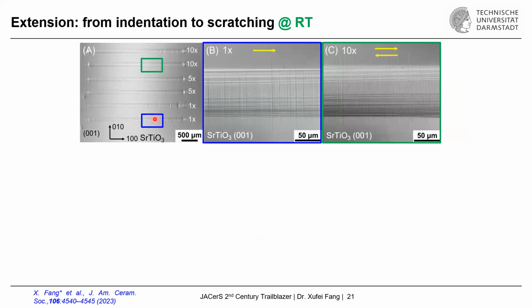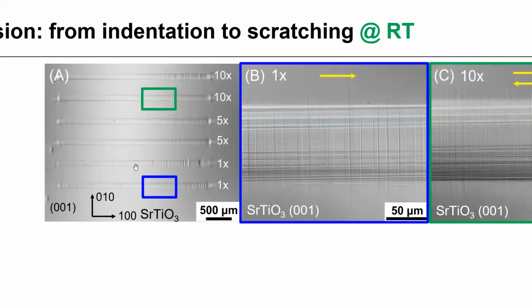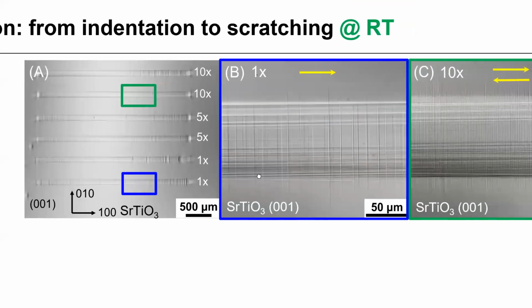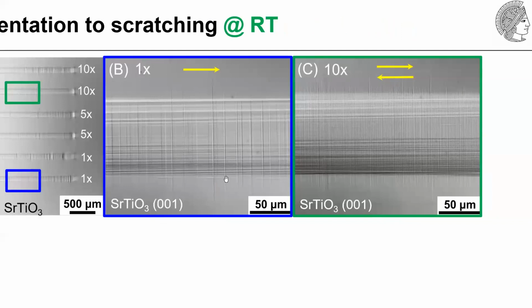Again, point loading using the indentation technique is not sufficient to generate a much larger plastic zone. That is why we started extending the indentation to scratching. And here I show you the cyclic scratching method. This is one cycle, just for reproducibility, 5 cycles, meaning that we scratch back and forth 5 times, and back and forth 10 times. Again, you can see the slip traces, the signature of the plastic deformation. For 1 cycle, it's rather discrete, and for 10 cycles, the density gets higher and higher. So that's, again, an indication of the high dislocation density.